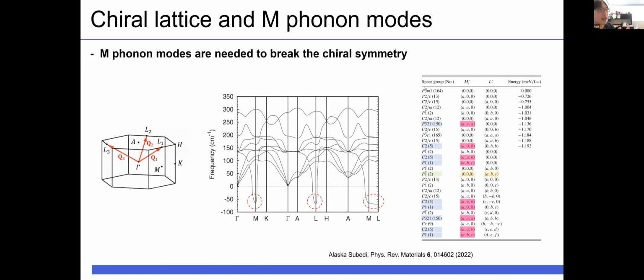We would say that it's the M phonon mode. According to the DFT done by Alaska, the phonon instability is expected along the LM direction. They have negative energy. Therefore, it's natural to think of displacement along the M points like the L phonon, and it can break chirality. In the right table, possible space groups from the combination of L modes and M modes are calculated,